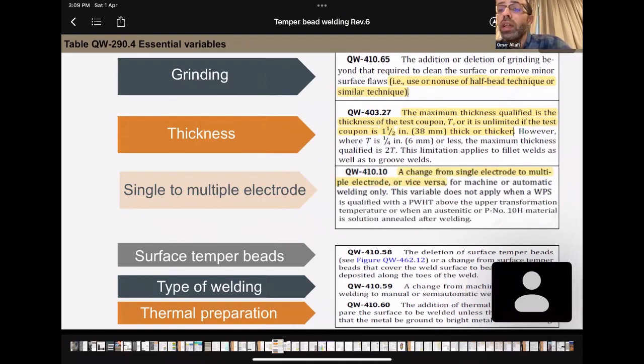The thickness is an essential variable for hardness, not for toughness, by the way. The maximum thickness qualified is the thickness of the test coupon, or it is unlimited if the test coupon is greater than 38 mm. So when you are welding the test coupon, its thickness is usually the maximum thickness you can use for temper bead. But when it comes to toughness, reduction of the thickness is not allowed.